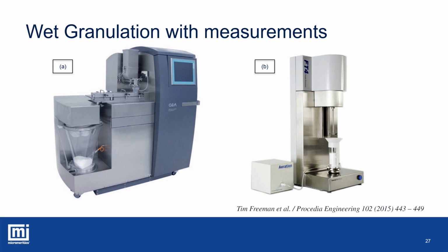This showed for both formulations that altering the process conditions, screw speed, solid feed rate and water feed rate produced a wide range of granules with differing BFE results. So far, so good, but what does this tell us?